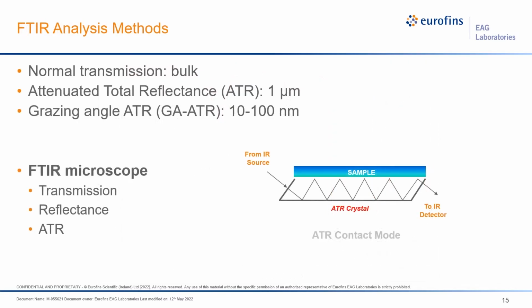Now, there are different ways to do FTIR. ATR measurement is a surface-sensitive measurement. You can do grazing angle ATR, which is also a surface-sensitive method. In this case, because we have a wafer, which is a very nice substrate for FTIR, we're just going to do transmission, but using the microscope. So micro transmission FTIR.